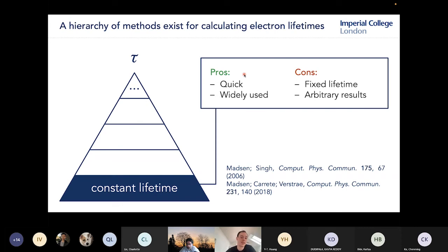And so the benefit is that this is extremely quick to do, and because of that, it's very widely used. But as you can imagine, you're using a fixed lifetime for every electron, which isn't correct. And you're also choosing an arbitrary value. Basically what this means is that any mobilities or transport properties that you calculate using a constant lifetime are again just going to be arbitrary, and you could scale them just by adjusting this lifetime.